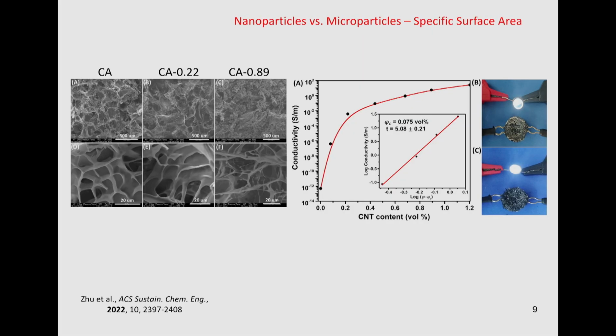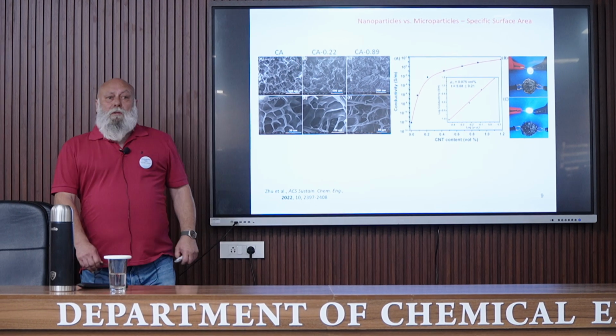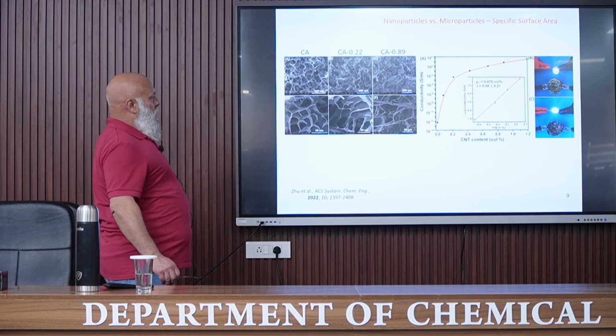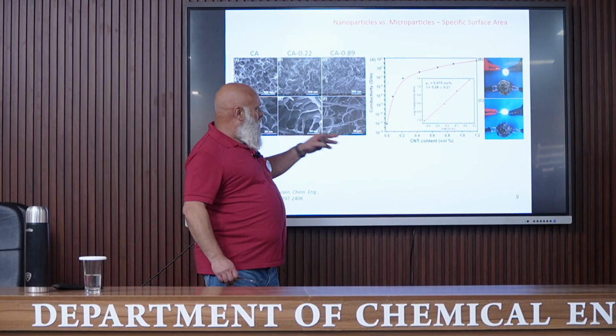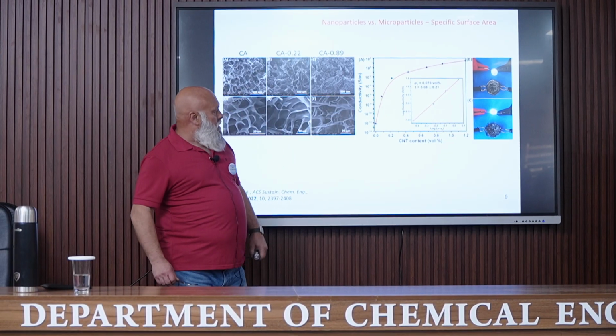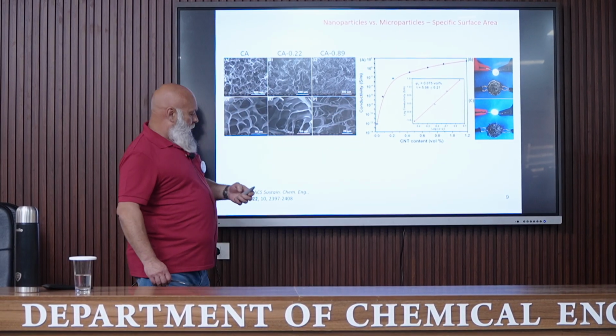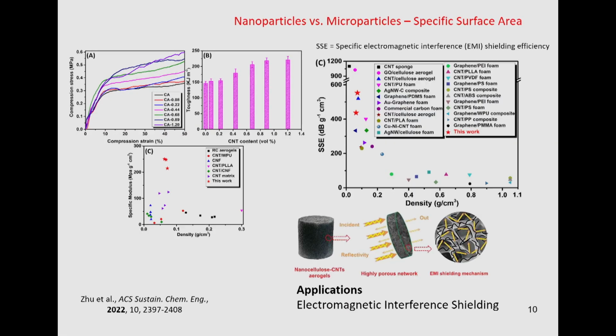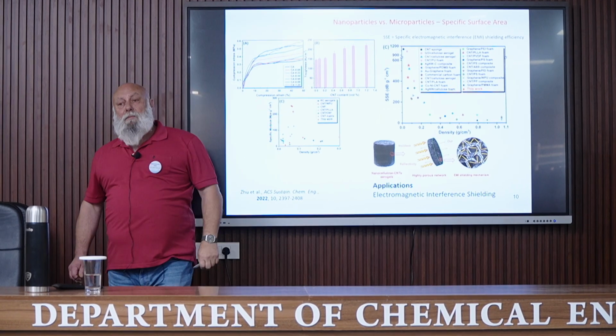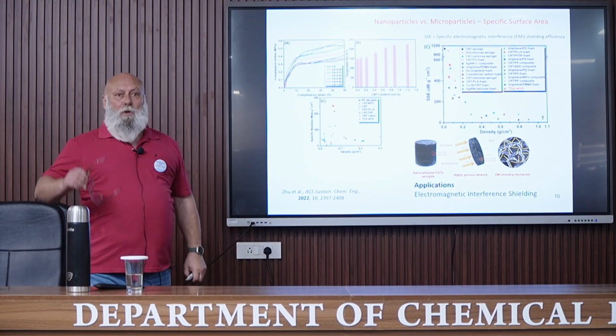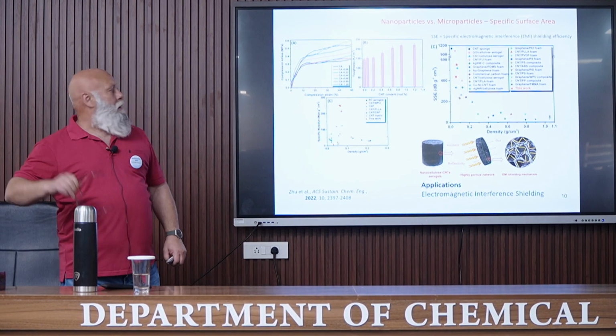So this is just the aspect of the cryogel, the pure cryogel, and here with 0.22 or 0.89% carbon nanotubes. So, of course, these carbon nanotubes give some conductive properties to the material. You can see the evolution of the conductivity as a function of the carbon nanotube content. And also, we don't discuss this too much, but it improves the mechanical properties. For example, with our tensile test, here we can see the toughness of the material. The toughness corresponds to the area under the stress strain curve.